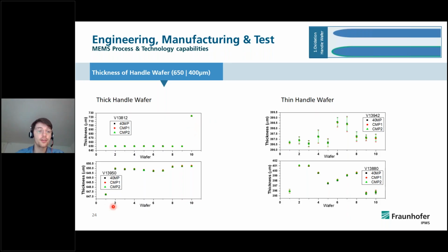So what we can see is there's always an outlier here for our processing. Here is wafer 10 and here's wafer 1. For the thin handle wafers, we have a deviation which is not that critical as we see at the thick handle wafers. But this will become a challenge later on in the processing, as you will see.